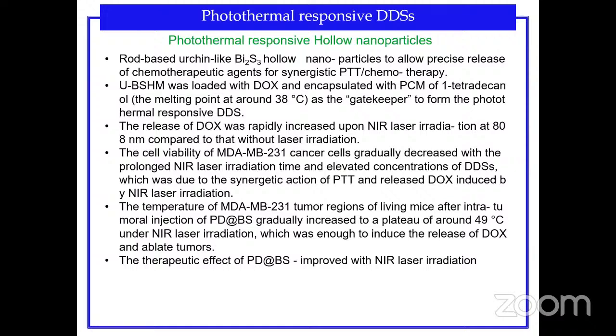Similarly, there is another system we can talk about, the photothermal responsive hollow nanoparticles, where the system has been developed like bismuth sulfide hollow nanoparticles, which are able to provide photothermal as well as some chemotherapy. So the bismuth sulfide nanoparticles along with doxorubicin are loaded in a mesoporous silica, which has been activated by light at 808 nanometers.